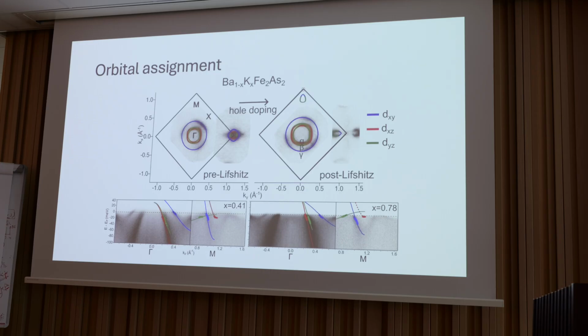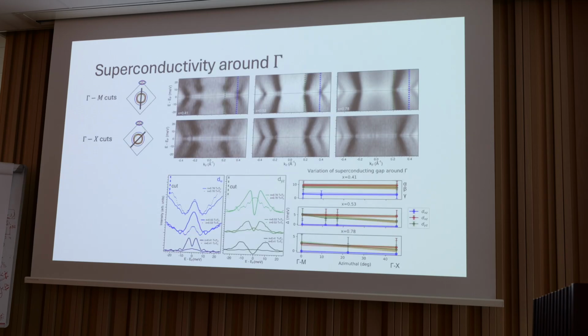And then using different experimental geometries, we can do some orbital assignment, and we confirm that the innermost are XZ-YZ character, and the outermost being the DXY bands, and then this DXY electron pocket and DXZ-YZ, which becomes YZ-XY. And something I can point out: the dots here are the experimentally fit bands, overlaid with the DFT, which I'll talk more about later. But you can see at 78%, I have this dotted line here. We see that the YZ band crosses the Fermi level. So we expect the XZ pocket to not be there anymore, but we still have some signatures of it. I'll talk about that a bit more later.